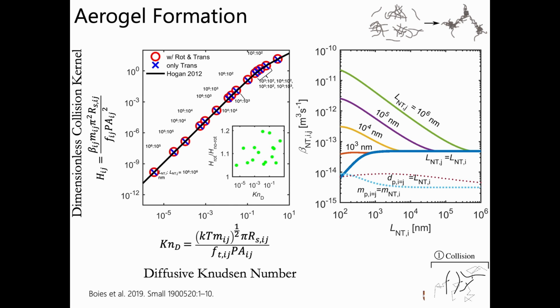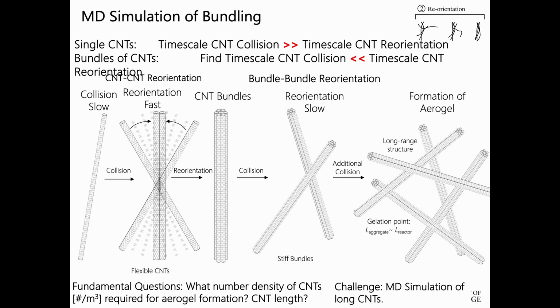And what's interesting about beta for rods is that it's an order of magnitude larger than spheres are. So what's shown in these dotted lines here are spheres of either the same mass, in other words, you can think of a nanotube being collapsed down into the same mass at the same density, or a sphere that is as large as the nanotube is long, right? And either one of those is an order of magnitude lower collision rate than the nanotubes. And that's why we don't see self-assembly of particles in a flame, let's say, right? We produce lots of soot in flames, and carbon black production is optimized for soot production or carbon production. We don't see self-assembly in that way, but yet these nanotubes we do, and this is fundamentally the reason why.